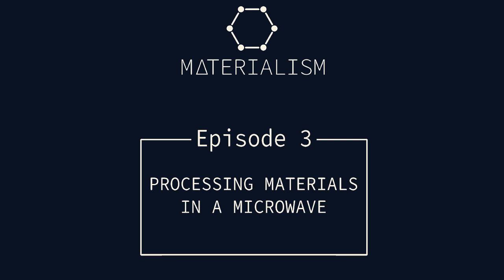So I thought about what material class I would like to work on, and I thought about carbides, because in addition to the microwave technique, carbides are basically the perfect choice, because graphite carbon couples very strongly to the microwave radiation. So you already have something that couples very effectively and efficiently to the microwave radiation inside your precursor mixture. So you not only have this external susceptor heating effect, you have an internal heating effect from inside of your reaction mixture as well. And that guarantees very, very high temperatures. And it is known that you need very, very high temperatures to prepare these carbides that belong to the family of MAX phases.